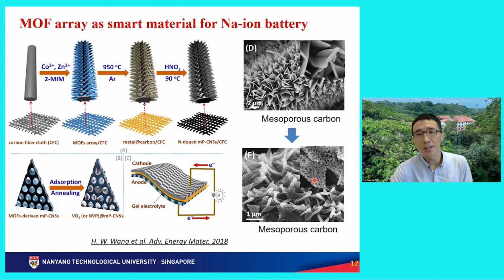Okay, so this carbon flakes we can use as three-dimensional current collectors, and then on the surface we can deposit by solution adsorption reactions. We can get both anode materials as well as the cathode materials. Okay, as I mentioned in the previous slide, this is just another way to realize the high rate performance using this MOF as a precursor.